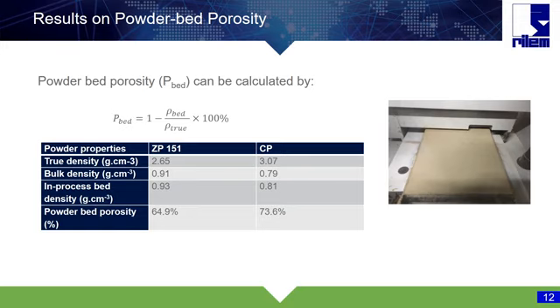You can see the results for the powder bed porosity. The powder bed porosity can be found by this formula as you see on the screen. So basically we can find how it differs between the two materials when we use ZP, or gypsum, and the cement mortar materials. We find the powder bed porosity inside them is about 64.9% in gypsum and about 73% in cement.